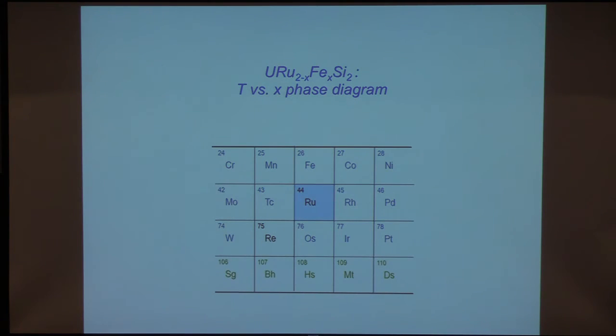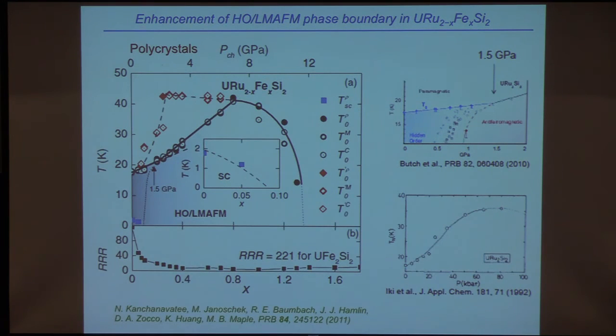Okay, so here then is the Tc versus x phase diagram. So again, we're substituting, in this case, iron for ruthenium. It's isoelectronic. And so in the early exploratory experiments with polycrystals, this is the only way you can work fast enough to do these exploratory things. We found that temperature versus iron composition gives you a phase diagram that looks like this. And these are little spurious features due to the fact that we're working with polycrystals, so just disregard them.